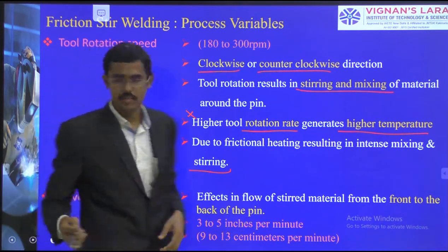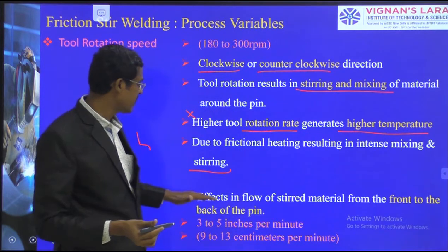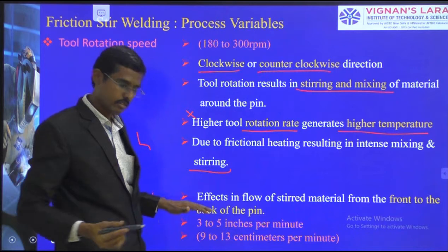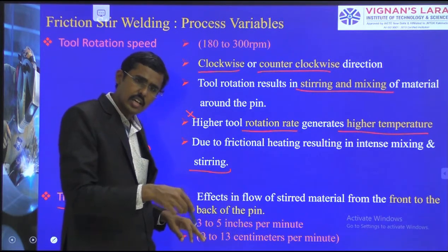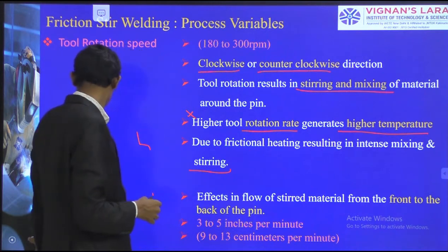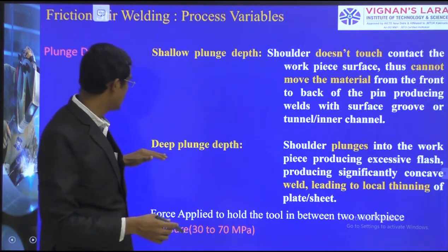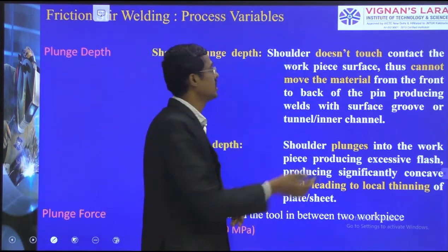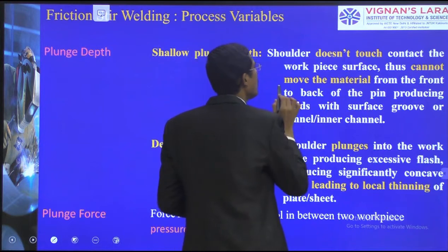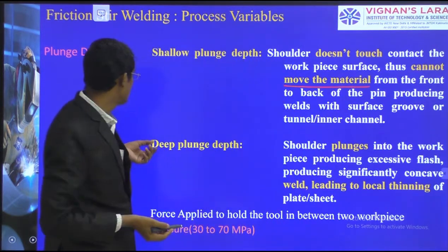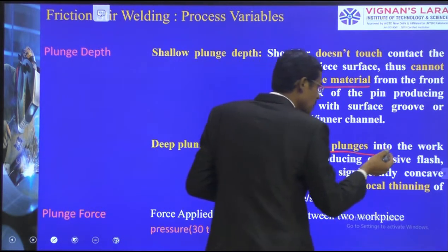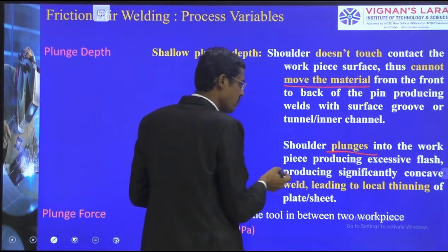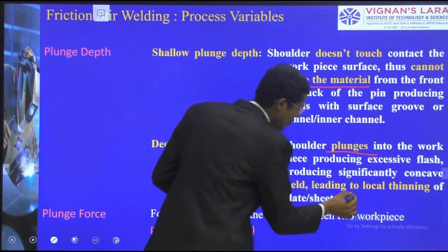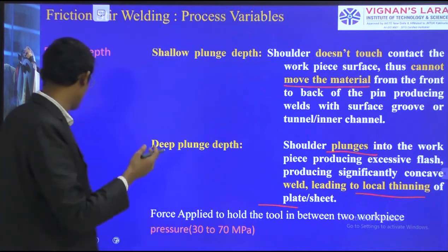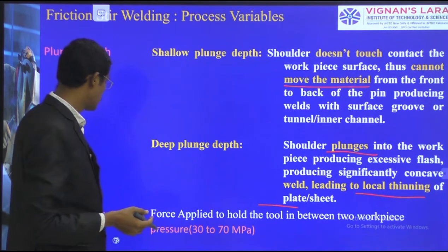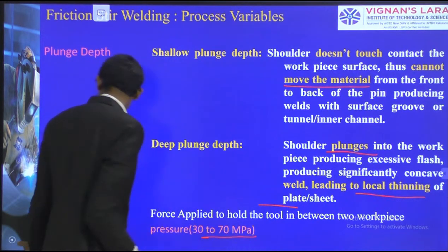Yes. Travel speed, we have just seen this. It affects the flow of stirred material from the front to the back. How fast it is moving, accordingly the stirring and the mixing will happen there. So shallow plunge depth and deep plunge depth, which one do we need? Shallow plunge depth does not touch the workpiece surface and thus cannot move the material. But in the deep plunging method, the shoulder plunges into the workpiece, produces excessive flash, produces a significantly concave weld and leads to local thinning of the plates. So this is to be taken care of. One more is there, plunging force, around 30 to 70 megapascals.